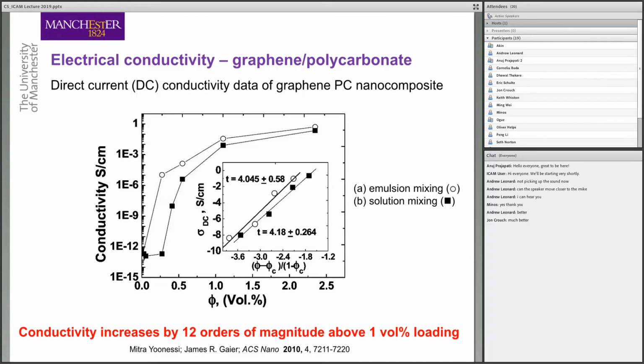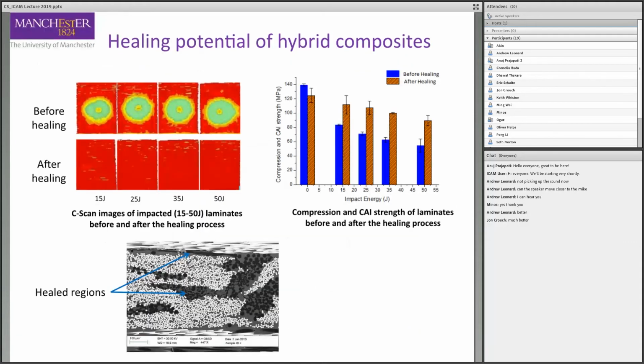We spoke earlier about the healing potential of the hybrid composites, where we had the plate under impact, where we managed by heating to repair the resin cracks and the delaminations. And of course, if we have graphene in our resin, then graphene will increase dramatically the thermal conductivity of the epoxy resin and speed up the healing process.